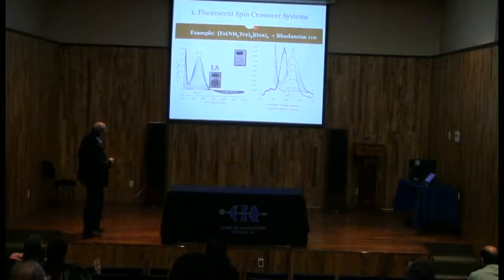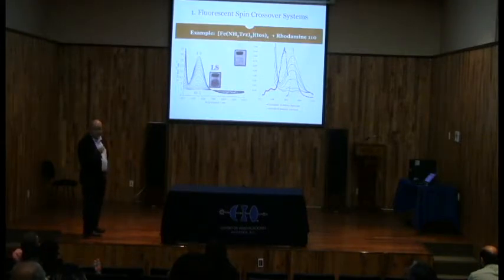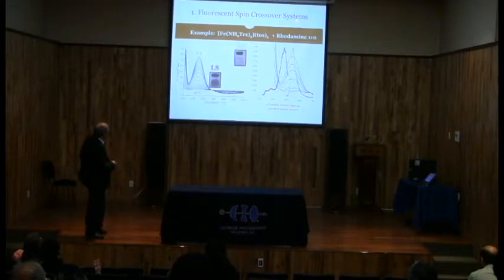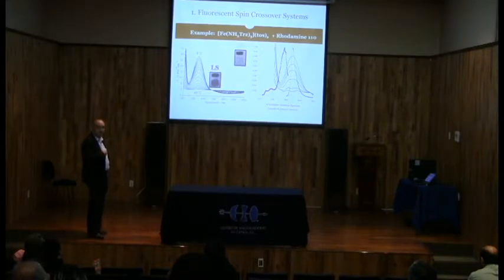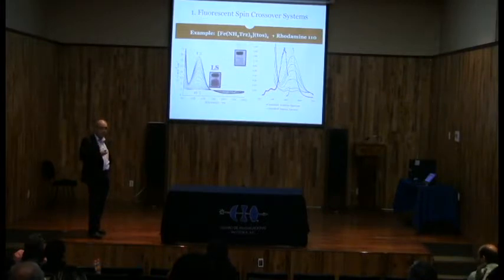That means that if you combine these two complexes, spin crossover and rhodamine 110, if you are in the low spin form, the light of the rhodamine, the green light, is absorbed, but if you are in the high spin form, there is no absorption. That means that through the spin crossover by temperature, you expect to switch the luminescence of the rhodamine.